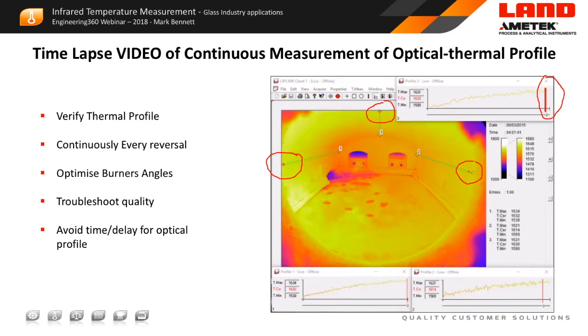So this allows you to do a great deal of work in terms of optimizing the fuel that's going into the tank. Now, because you're measuring the whole area, you can also look within the tank if there's any areas that are getting too hot, and particularly if there's any areas that are getting cold with air ingress, which wastes energy, totally waste of energy if you have an air leak into the furnace. And if you have an air leak into the furnace, you get condensates, and the condensates will destroy the refractory. So asset protection using this device is a very important part of what we're giving as part of the solution.